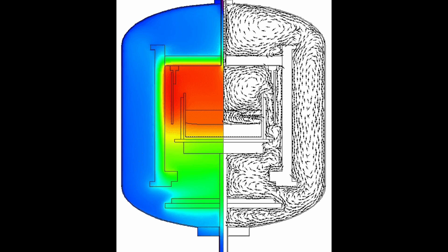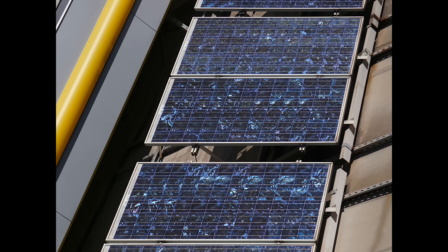Crystals made with directional solidification tend to have more defects than their single crystal cohorts. Dislocations due to thermal stress tend to have unpredictable outcomes on the panel's final solar efficiency and longevity. On the other hand, multi-crystal silicon is far cheaper to make. And over time, the industry has managed to reduce the defect rate and thus improve the panel's efficiency in production from just 8% in 1980 to 18% today. For these reasons, multi-crystal silicon solar cells currently dominate the industry, with some 60-70% market share depending on what source you look at.